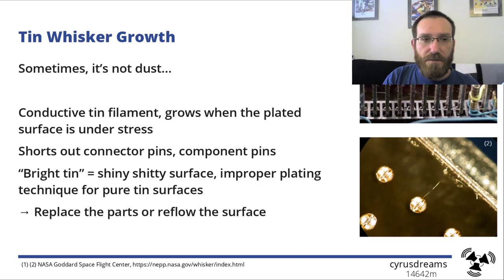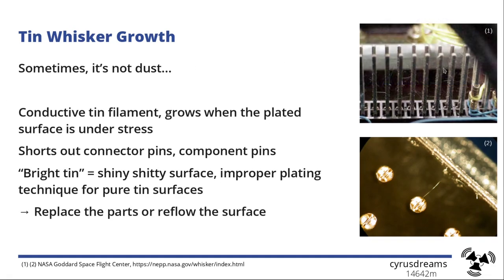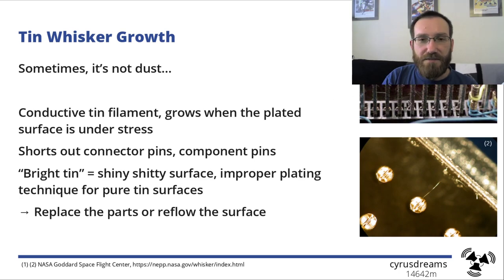And there's something that not many people know about, that's called tin whisker growth. That happens on tinned surfaces, which are only tin and not tin-lead. And actually, leaded tin was introduced in the 1940s to prevent the tin whisker growth from happening. So what you will have here is small filaments that go from one connector to the other one, and I have seen them in real time in connector shells like this. That photo is not from me, but mine looked exactly the same, where the outer housing, which is normally grounded, has grown a tin whisker to one of the active pins and shorted that out.